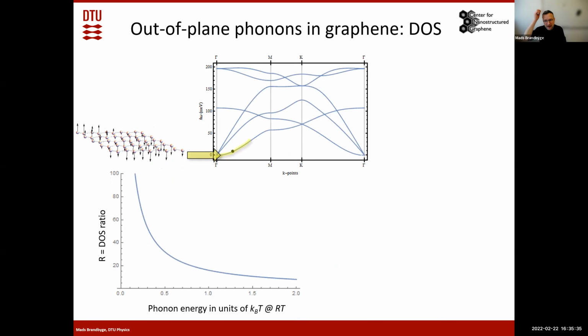So we gave this some thought, and we proposed that maybe when you have gated devices, the gate breaks the symmetry. And what is the importance of this symmetry breaking? Well, when you have 2D materials, the out-of-plane modes are actually quite dominating. This is because the dispersion relation for the out-of-plane modes is actually quadratic when you go to low phonon energies. So quadratic dispersion in 2D means that the density of states is constant for these vibrational modes.